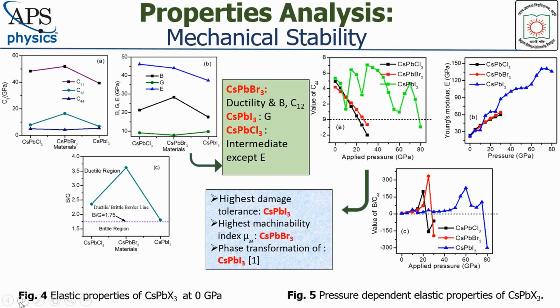From figure A, the threshold applied pressure above which cesium lead chloride and bromide lost the mechanical stability are 20 and 25 gigapascals, where it is 75 gigapascal for cesium lead iodide. Young's modulus increases with pressure for all of them, but the nature of increment is different for cesium lead iodide.